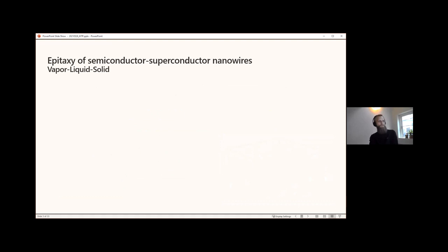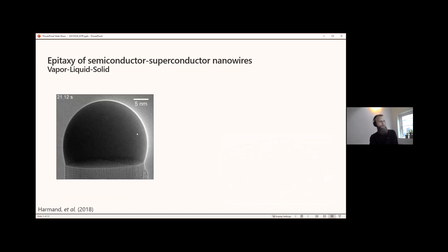While there are multiple ways to comprise such a system, in this work I'm going to be talking about the method which is dubbed vapor liquid solid, and here I'm just showing you an illustration of how these nanowires are grown. This is the end of the wire, TEM imaged in situ during the growth. And you see this ball. This is not a Majorana in this case. This is a gold catalyst, which basically collects the vapor III-V material from the surrounding, liquefies it, and then when it gets saturated, it solidifies it and forms the epitaxial material layer by layer.